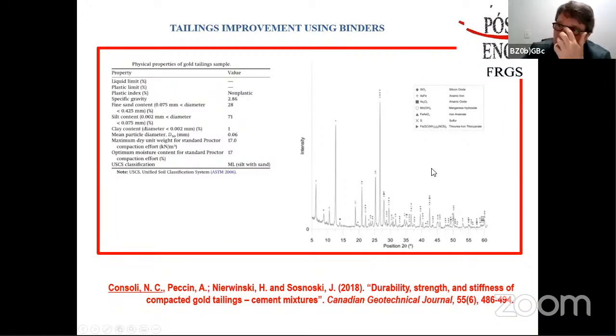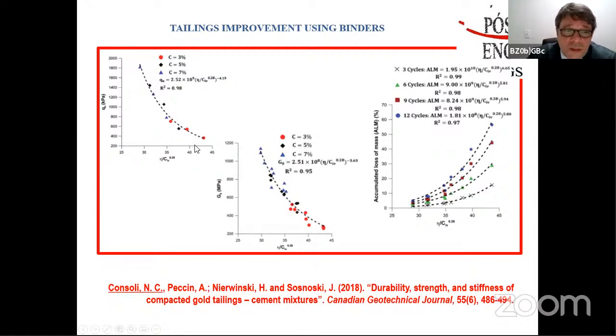And in this case, we decided to insert some amount of cement, and we have studied, and this is what was published in 2018 in the Canadian Geotechnical Journal. We studied the durability, the strength and stiffness of these mixes. And then we can see here, through the same index that we developed, that it controls the whole situation. Let's say the unconfined compressive strength changes in this way and through this equation here. So once again, if you have one point, you can draw the whole curve. Also, the initial stiffness is also a scalar here that is also controlled by this index.